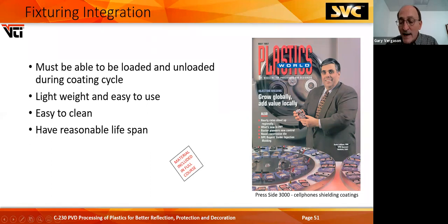These are Ericsson cell phones that were being coated in our Press Side 3000 at SPM Dynacast in California. So we had to mask. You can see some of the mask requirements on there. Inside each key area had to be masked. So these were cast masks that we made here at VTI. You would spend a lot of money trying to machine all those. So we actually made rubber tooling, multiple sets of the rubber tooling. And so we were casting 10 to 20 of these at a time.